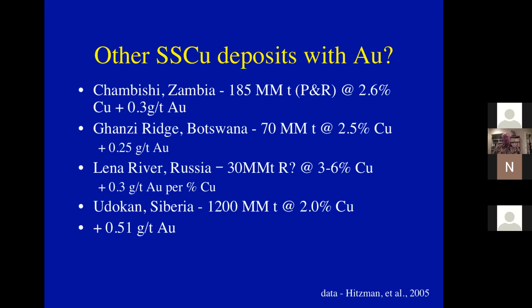The newly discovered deposits in Botswana, some of them at least have a quarter of a gram of gold. The Lena River deposits in Russia, we don't have a great deal of data on them in Hitzman's table in 2005, but they run between 3 and 6% copper with 0.3 grams of gold per percent of copper. So in the 6% copper stuff, you're talking about almost 2 grams of gold per ton. And Udokan in Siberia, which is a great 1.2 billion ton Proterozoic sandstone hosted copper deposit, has 2% copper and 0.5 gram of gold. And that's a lot of grams of gold in one of these systems.